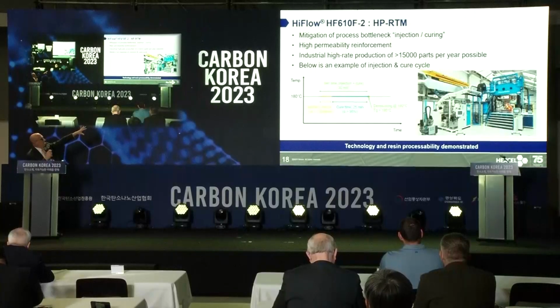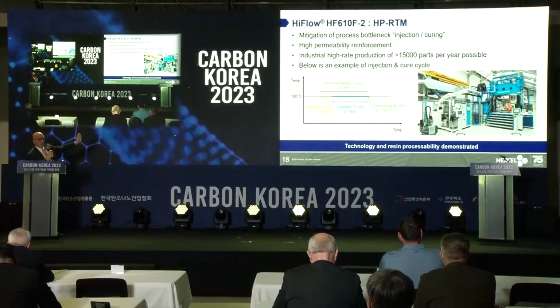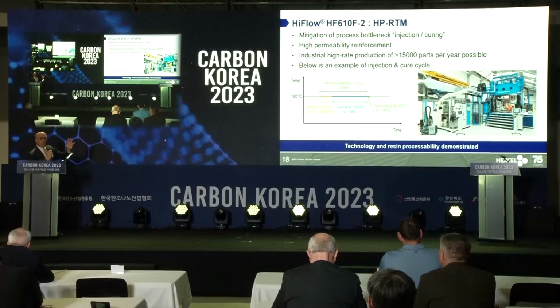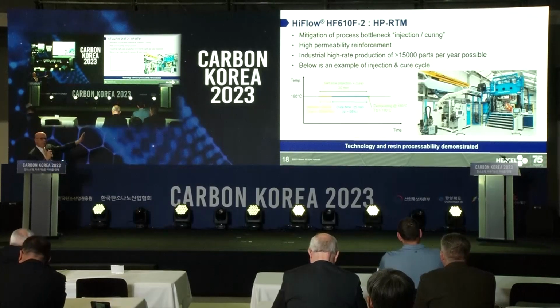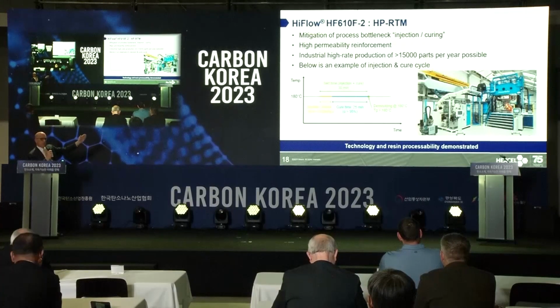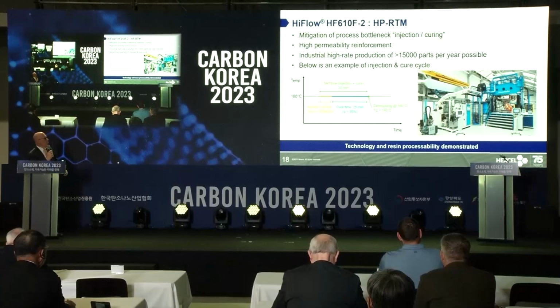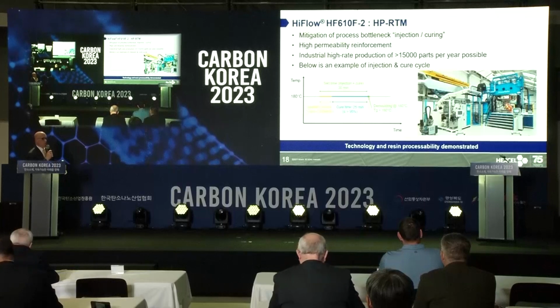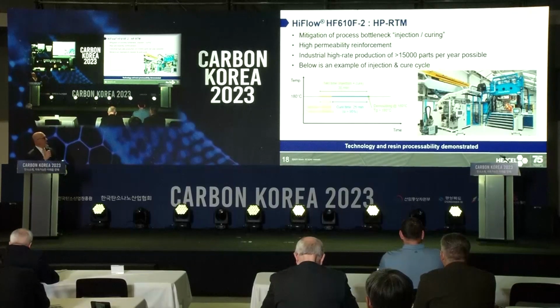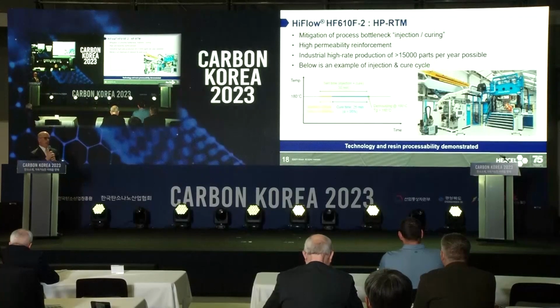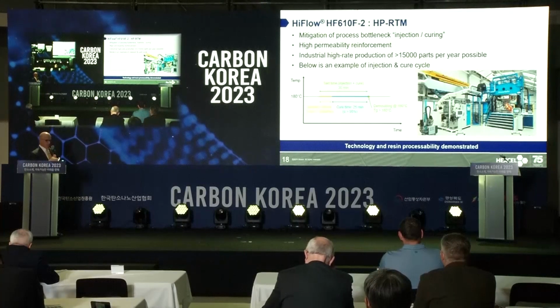So this 610F2 has very good viscosity for about 5 minutes for you to do the injection, and then the cure time is about 25 minutes. So a total cure time of 30 minutes from going into the press to getting it out of the press. And so that is going to be able to get up to rates like, as mentioned here, 15,000 parts per year possible. So this is a high rate system that has good mechanical properties.